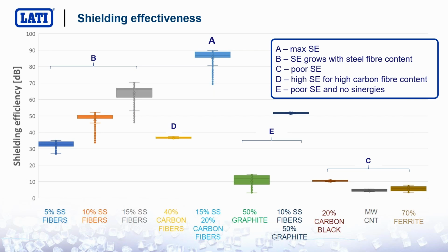Why is it important to keep developing this graphite and stainless steel solution? Because graphite is providing thermal conductivity. So if LATI is able to develop a perfectly EMI shielding and thermally conductive compound by maybe adding some carbon fiber to graphite and steel fiber, you can have a thermally conductive, heat dissipating solution, which is also EMI shielding. That's the reason why we will keep working in this direction.